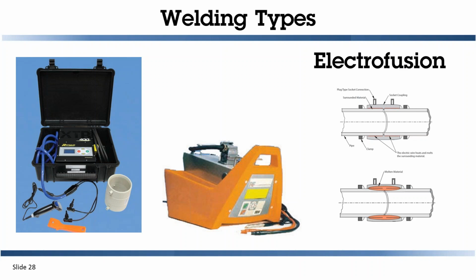Finally, we have electrofusion welding. Electrofusion has a coupling with a metal wire inserted in that coupling. You apply electricity to the coupling, and that heats up the joint. You then get the bonding of the pipe to the fitting and the fitting to the pipe. This is a great method for water installation. We use it a lot for repairs or changes in direction or hard to reach places like below grade or in a ceiling where you can't bring a butt fusion tool.